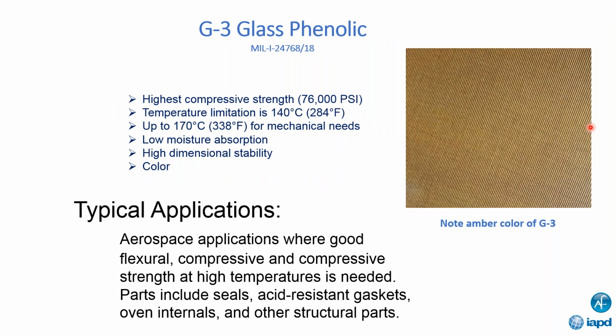And then the final member of the glass family here is the G3 glass phenolic. This is typically used in aerospace applications, and it's really noted for its amber color, which is exemplified by the picture on the right-hand side of the screen there. It's got great compressive strength. You see 76,000 PSI. That is our strongest structural material that we carry. Temperature range is 140 degrees C, but it can spike up to 170 degrees for mechanical applications. And again, low moisture absorption on this product.